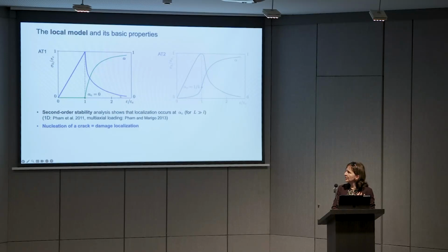having this curve essentially means that in 1D you start damaging here, so at the peak stress, but this doesn't tell you whether the damage will localize. So essentially this is a homogeneous response, right? We found this out by killing the Laplacian in our equations. But if you do a second order stability analysis, which you can do because you have an underlying energy functional, you can compute the second variation, you find out that at alpha C you do have localization, provided your bar is long enough.